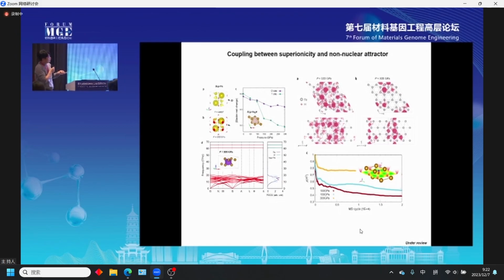So with increasing pressure, the portion of time staying at this site increases accordingly. At 300 gigapascal it stays much longer, around 80% of the time at this non-nuclear attractor site. This means the electride effect is much enhanced, and it is triggered at 100 gigapascal.